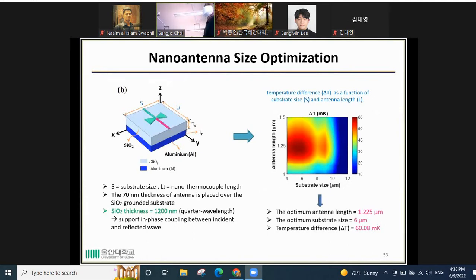This is the nano antenna size optimization. First, we optimize a single antenna. S is the substrate size, and LT is the length of the nano thermocouple. The antenna with 70 nanometer thickness is placed over the silicon dioxide grounded substrate, and we choose TS, which is the silicon dioxide thickness, to be 1.2 micrometer, or quarter wavelength, to support in-phase coupling between the incident and reflected wave.